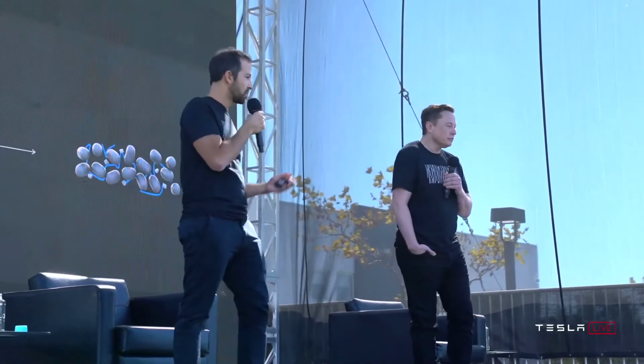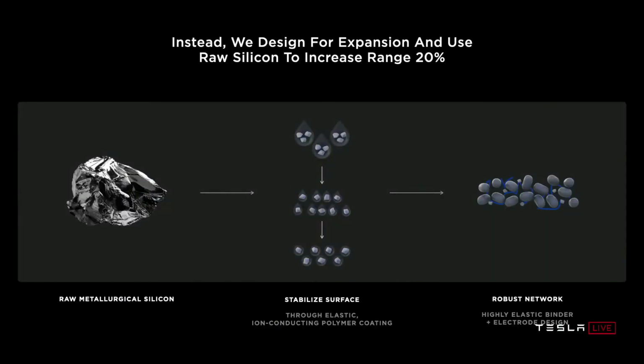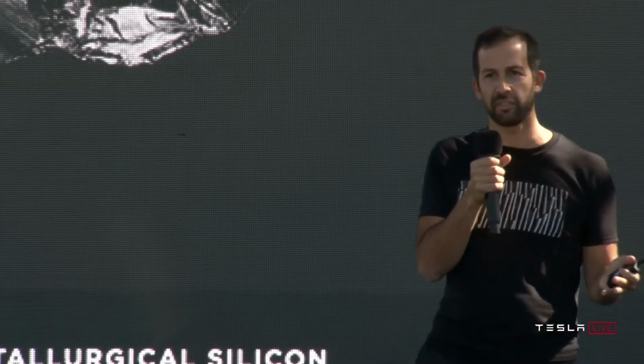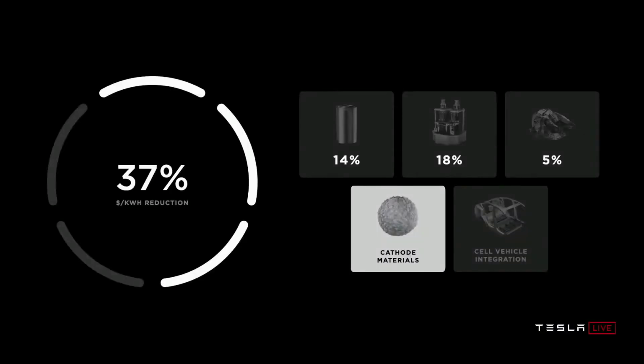And how does it work? Start with raw metallurgical silicon, stabilize the surface with an elastic ion-conducting polymer coating that is applied through a very scalable approach. No chemical vapor deposition, no highly engineered high capex solutions, and then integrated into the electrode through a robust network formed out of a highly elastic binder. And in the end, by leveraging this silicon to its potential, we can increase the range of our vehicles by an additional 20%, just this improvement. It gets cheaper and longer range. And when we take that anode cost reduction, we're looking at another 5% dollar per kilowatt hour reduction at the battery pack level. And there's more.